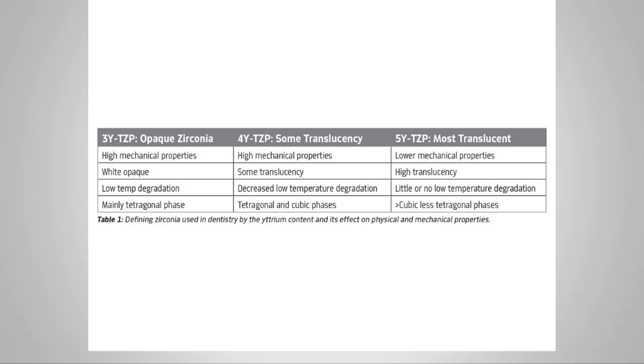You'll also see that it's mainly tetragonal phase zirconia, and there's going to be multiple phases that we see in zirconia. The 4 molar percentage yttrium stabilized zirconia is in the middle column. This is a relatively new category. The 4 and the 5 molar percentage are relatively new. And you can see how the different percentages of the yttrium change the properties. So still high mechanical properties, but the 4 molar does have some translucency. So now we're dealing with the tetragonal and cubic phases of the zirconia.